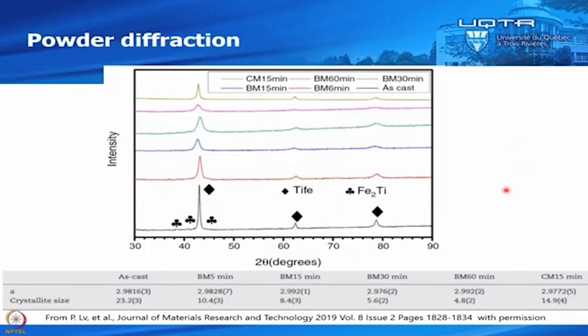So this is the X-ray diffraction pattern. So this is the as cast. You have iron titanium and also a little bit of iron 2 titanium. And when you mill, you see the peaks are getting broadened because it's getting a nanocrystalline structure. But we don't have formation of any new phase. So you see the crystallite size as cast is 23, and ball mill 5 minutes we already reduced it by a factor of 2, and it continued to be reduced.